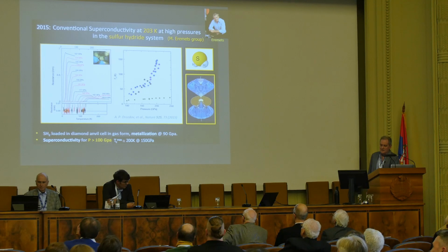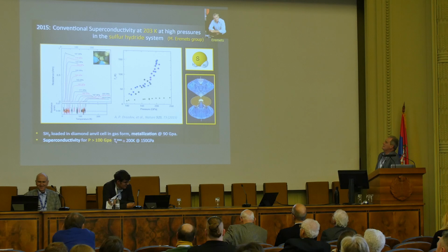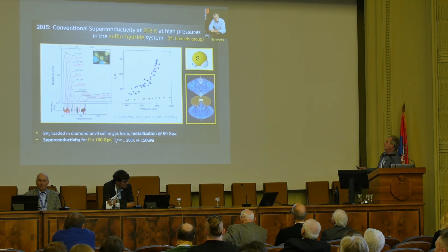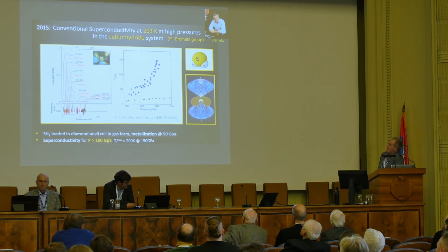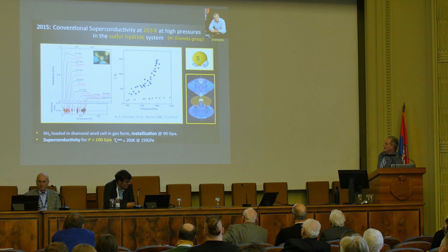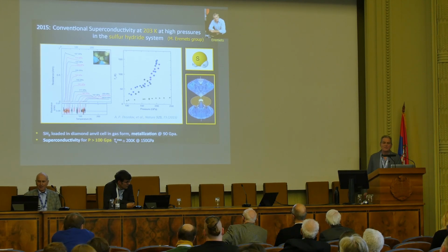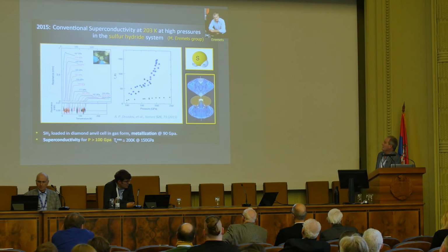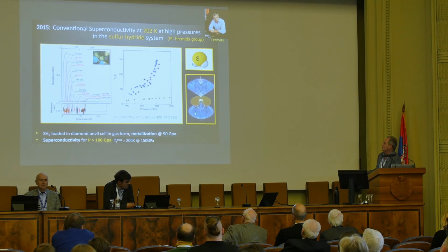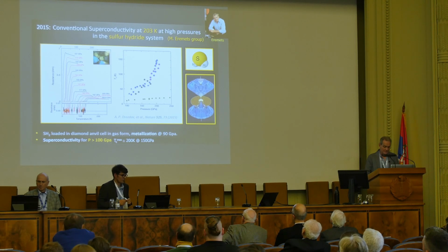I think if I'm a colloquium speaker, I'm allowed to talk a little bit about things that are interesting to me. And this is the experiment done by Mikhail Eremets in Mainz in 2015, where he discovered, to many people's surprise, superconductivity at 203 Kelvin in hydrogen sulfide under high pressure. Now, this is really high pressure. This is close to a megabar of pressure, more than a megabar, in fact. And it's obtained by putting two diamond anvil cells, squeezing them together with a metallic gasket. And you see that TC gets very high and eventually made it up to 203.